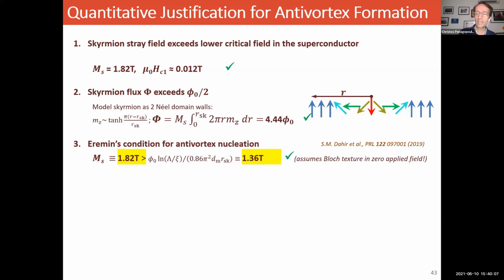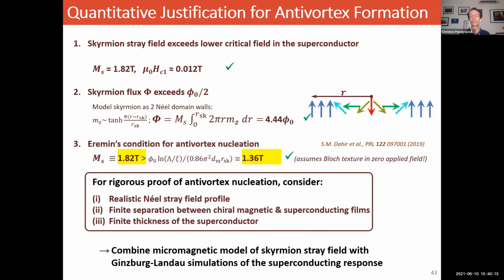But remember, this is for Bloch textures. And I mentioned before that we have shown through Bartendu's work that we have Néel skyrmions. So if you want to have a rigorous proof of anti-vortex nucleation in our heterostructures, or at all with Néel skyrmions, you should consider a realistic Néel stray field profile, finite separation between chiral magnetic and superconducting layers, and a finite thickness of the superconductor. And in order to do that and be absolutely certain, we combine a micromagnetic model of skyrmion stray field with Ginzburg-Landau simulations of the superconducting response. And we do the calculations.